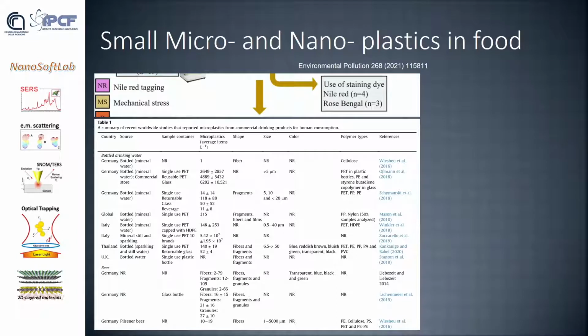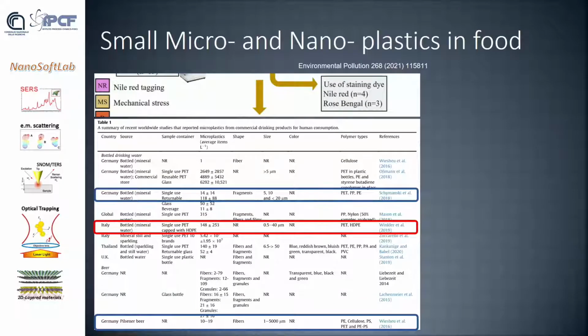Okay, I've seen, interestingly, that micro and nanoplastics can be found in drinking objects. Basically, in this very recent review published in 2021, I've seen that fragments of small plastics, meaning dimensions of 5 to 10 to 20 microns, have been found in Germany in bottled water, also in beer. And very interestingly, in bottled mineral water in Italy, it was found that particles ranging down to 500 nanometers, meaning in the nano scale regime, have been found. So in drinks, we can find small microplastics and even nanoplastics.